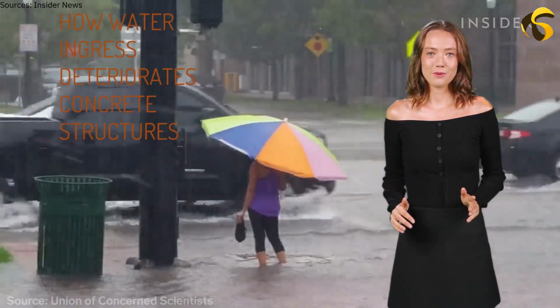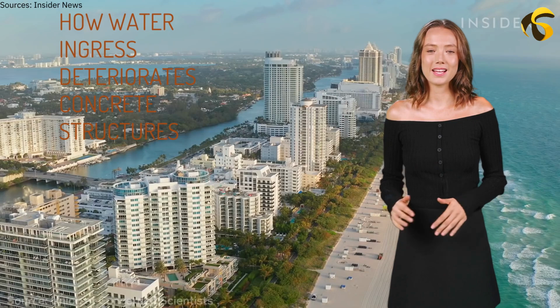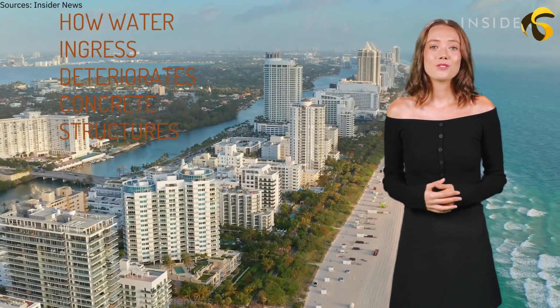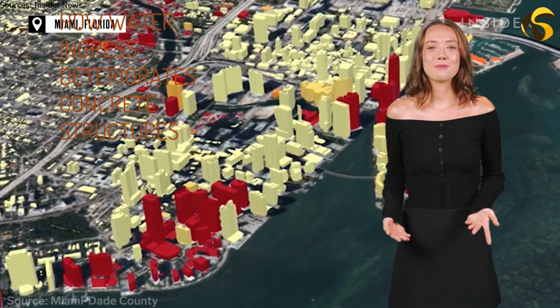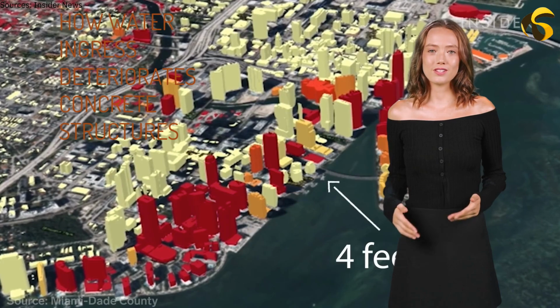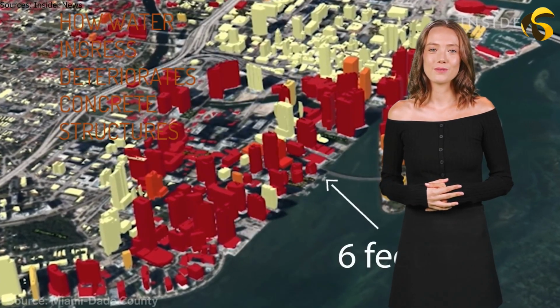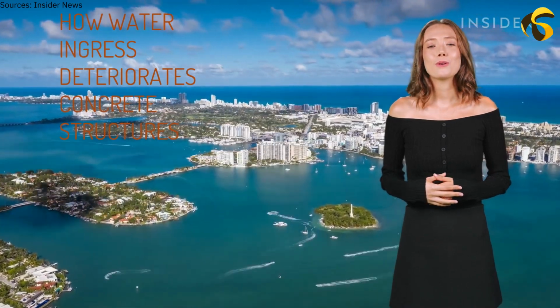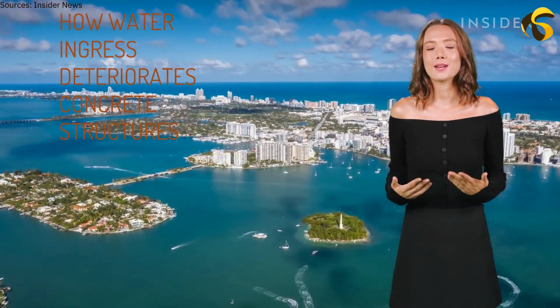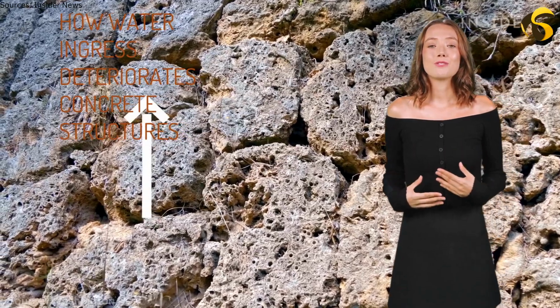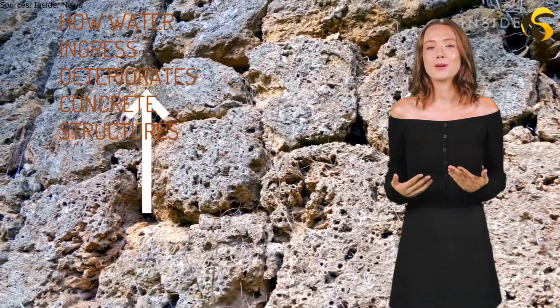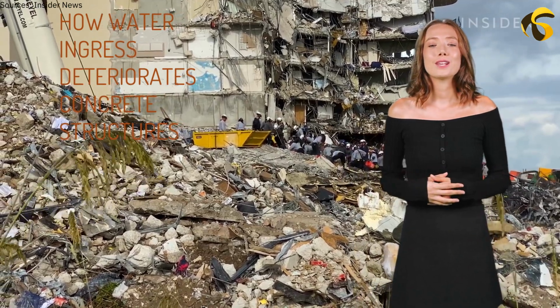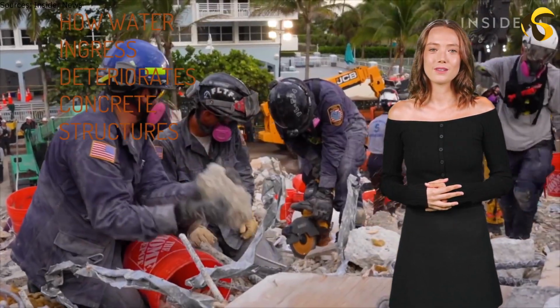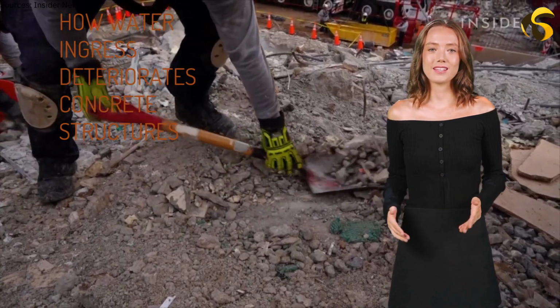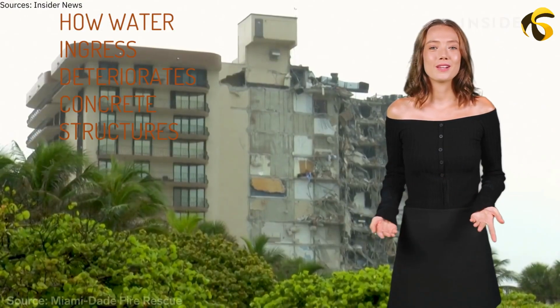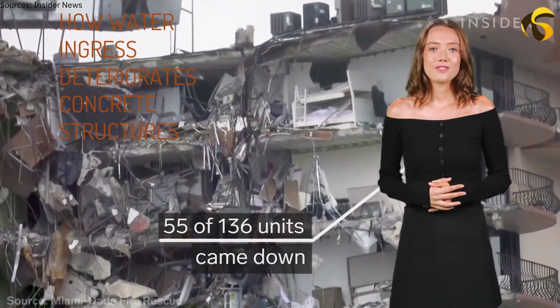But in the presence of water and oxygen, once chloride has breached the concrete cover, corrosion will proceed rapidly. Champlain Towers South, situated near the ocean and built over a saltwater water table, was undoubtedly exposed to chloride sources. Sea salt in the air, wind-blown salt spray, and possibly saltwater intrusion from below could all contribute chlorides. Additionally, the pool deck might have been exposed to salts. Chloride attack likely worked in tandem with carbonation and directly with water to corrode the rebar over the years.